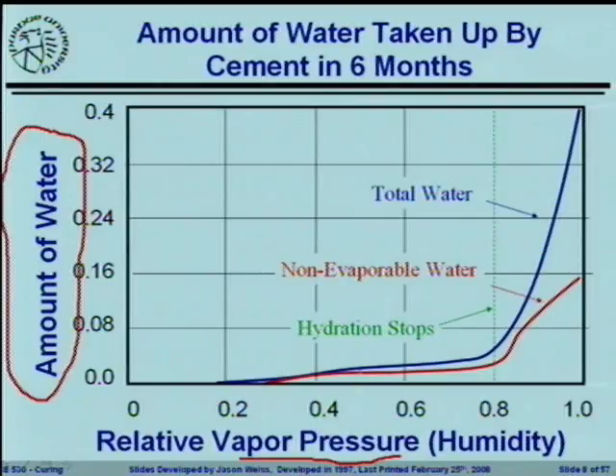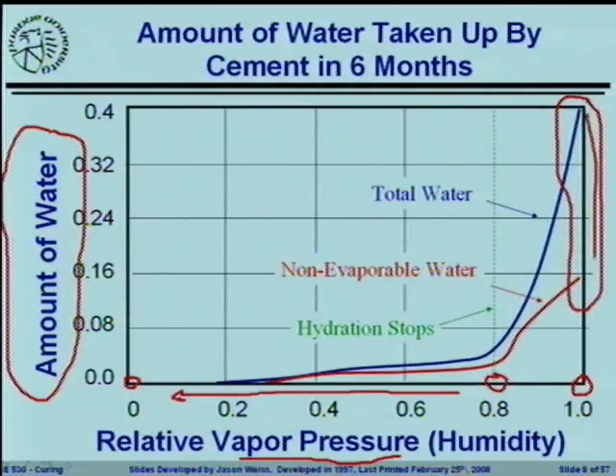The basic idea here is Powers took some cement powder and he kept them in 100% humidity, 80% humidity, all the way down to 0% humidity. Very dry system. All right. What he measured was how much water would be taken up by that powder to be participating in the reaction. And not surprisingly, you can start to see that the amount of water that's absorbed by these different powders depends upon the relative humidity that the powder was exposed to. The higher the relative humidity, 100% relative humidity, you see a lot of water is taken up by the system. Some of this water may or may not react, but a lot of this water has reacted.